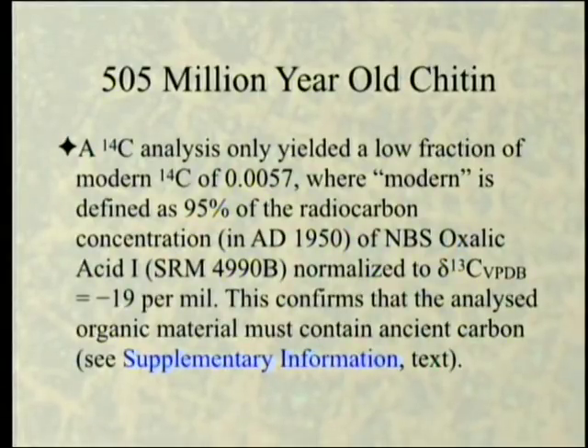You see, what they did is a carbon 14 date, and they're reporting it as fraction modern carbon. And what that means is that 99.4% of the material they're getting dates old, at least 99.4. That you can't put more than about 0.5%, 0.0057, I think it is. We'll see. We'll get that date a little more accurately later. That you can't put more than 1/200th or so, 1/180th of the material as new stuff, at least new from the last 5,000 years or so.